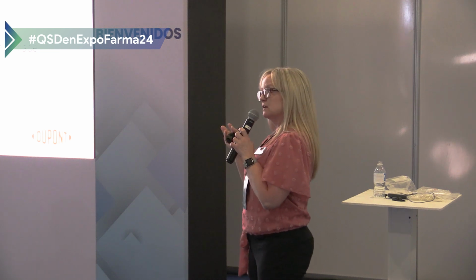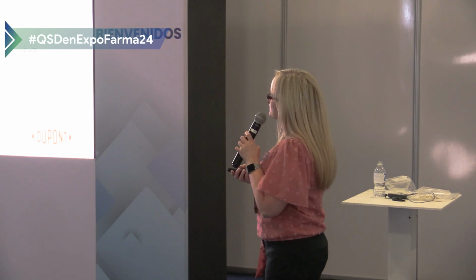So with the processing of the PSAs, one of the advantages to these is you actually coat it onto your release liner that you're going to use, and then you can transfer coat it onto any type of substrate that it will adhere to. So if you have more of a lighter weave material, something like that, it can be transfer coated onto that material, so you don't have to cure it right on it like an SSA. With these, again, the adhesive itself is already made during the reaction process. So really, with this one, you're not doing any type of reaction. You are just drying off the solvent in order to leave the remaining adhesive.